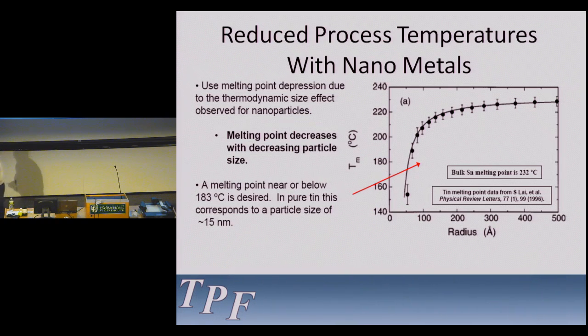So this is an area that I've spent a fair amount of time in, is reducing the process temperature with nanometals. We all learn in analytical chemistry that melting points are absolute. Well, they're absolute until you get below about 30 nanometers. And then they start to reduce, and that's because the surface energy becomes higher, and you've basically got stored energy in the particles, so they'll melt at a lower temperature.